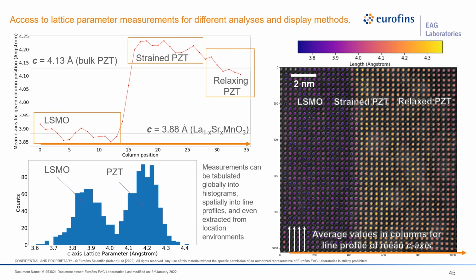This is an example of strained PZT on LSMO material. We can use some software to find the centers of every atomic column in the crystal, and then we can color code them relative to their average value for lattice spacing in the C-axis. Then if we take an average line profile here, we can plot this, and you can see here's LSMO on the left. Typically it's 3.8 angstroms, so we can see how that value targets right around that. And then at the interface, we can see that there's a region of strained PZT that then relaxes back towards the known bulk PZT value.